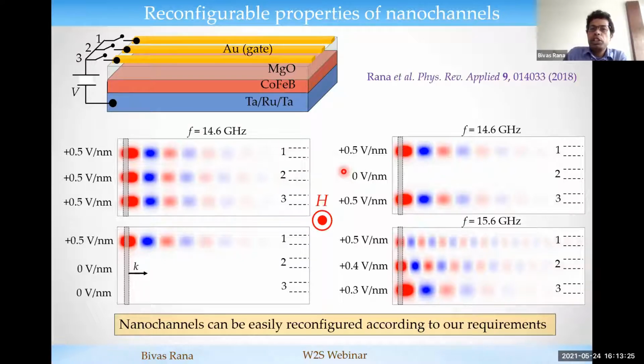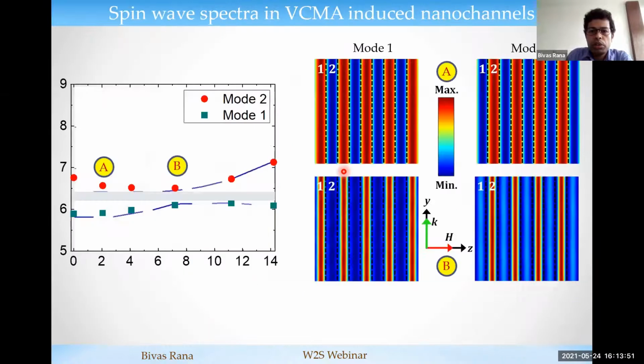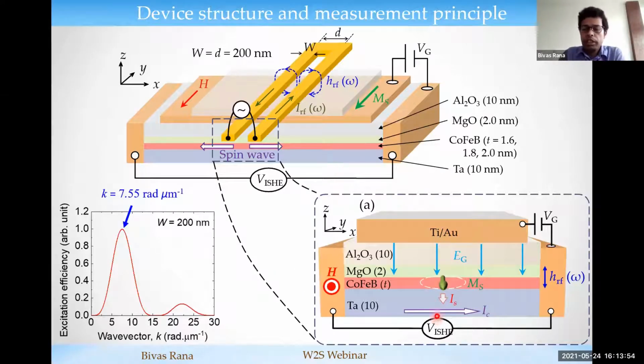Okay. With perpendicular anisotropy, the magnetization is oriented in the out-of-plane direction, and in other cases in the in-plane direction, right? No, there is no in-plane. It's just a heavy metal and a ferromagnet, but the ferromagnet has PMA. Yes. Then how do you explain the spin pumping and ISHE? Okay. So I go to this slide probably. Here I have shown that in my case we have a perpendicular anisotropy in the system which we can modulate, but the easy axis in our case was in the plane of the film, because we apply the magnetic field also in plane.